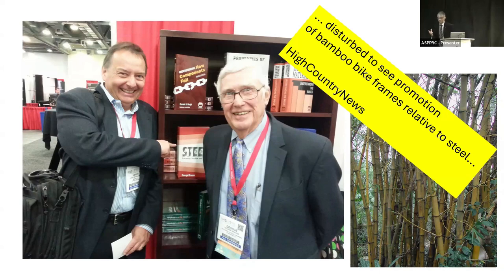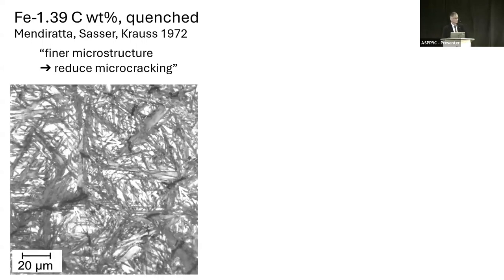You can't create a steel center without having a real passion for the subject. You have to remember that. It isn't just about creating a steel center, but you really believe what you're doing. And I met him actually around 1980 when he came over to Cambridge to see Professor Robert Honeycombe. And before that, I had read a paper by him, which was in 1972, where he quenched a high carbon steel. And you can see microscopic cracks in the martensite plates here.